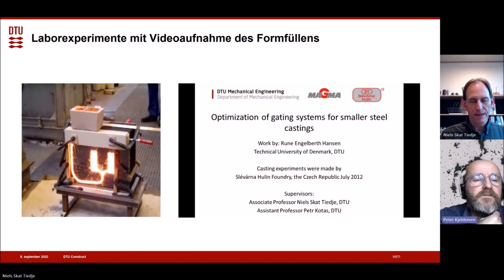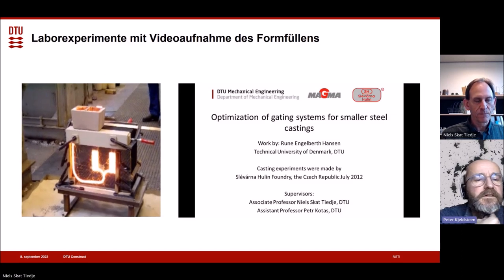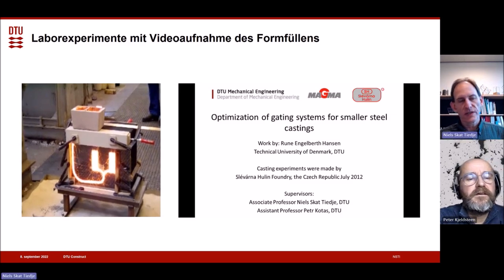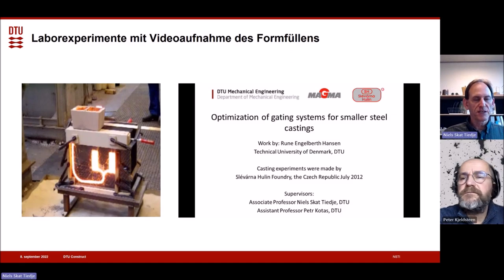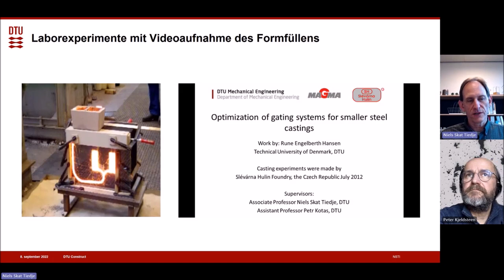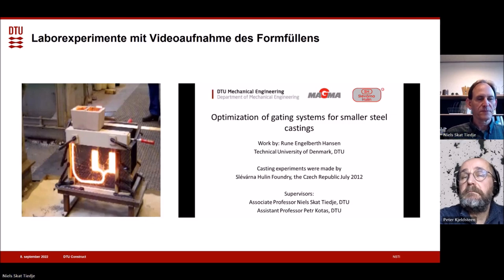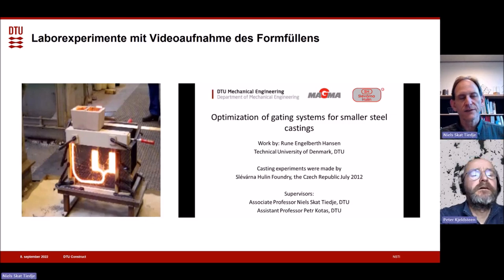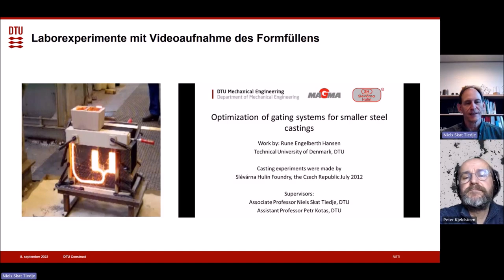Yeah. And what is the thickness of the structures? The one I show here is just an example, but it was actually a gating system we designed for a thin-walled manifold. And we managed to make a four-cylinder manifold with a wall thickness of 2 millimeters in cast iron, with dimensional accuracy of about a tenth of a millimeter, which I actually think was pretty impressive.